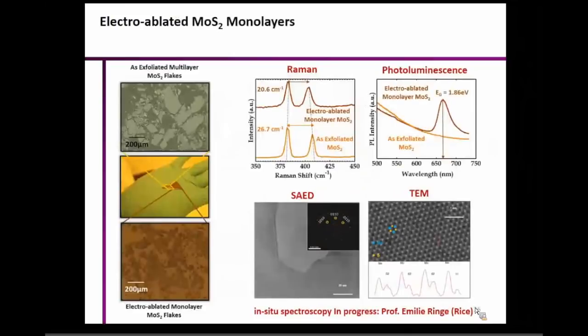Right. And then we, of course, did a lot of characterization to figure out whether these layers which are left behind are actually monolayers. So we have Raman, PL, and TEM showing that these are actually monolayers. And in fact, we all know that when you treat these 2D materials with chemicals, there could be a phase transformation. You could go from the 2H to the 1T phase, and that would be a semiconductor to metal transition, which you do not want for electronic device applications, right? You still want to preserve this 2H semiconducting phase, and the TEM actually confirmed that.